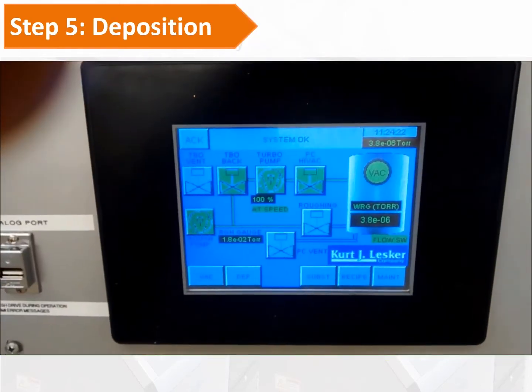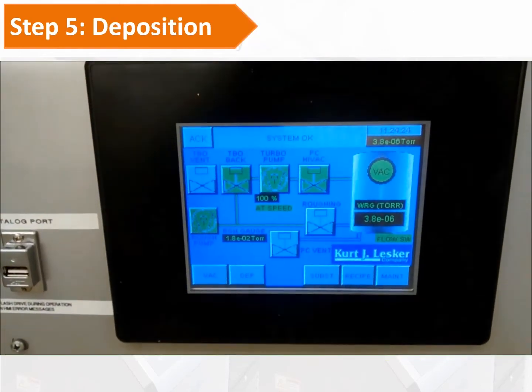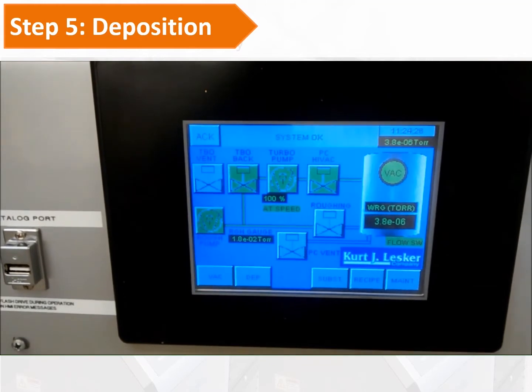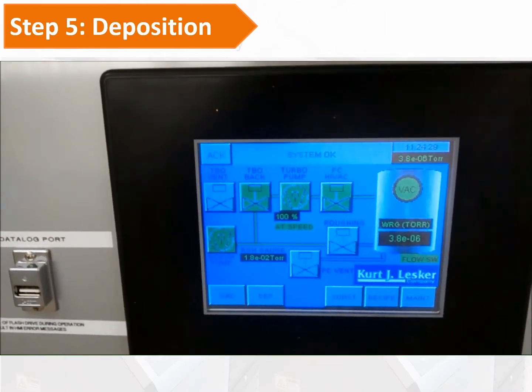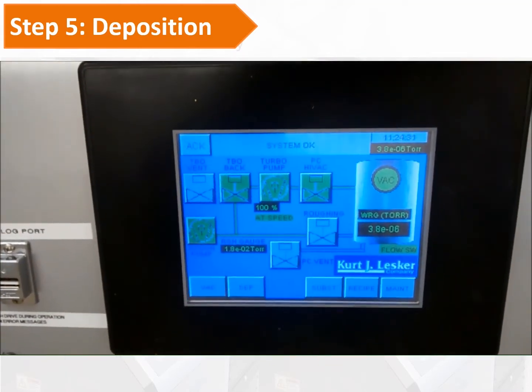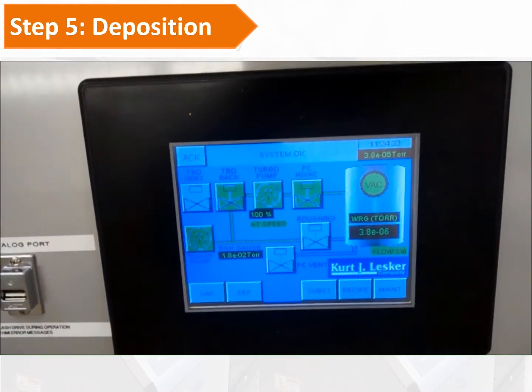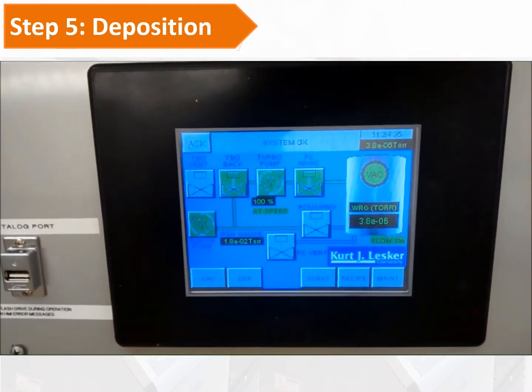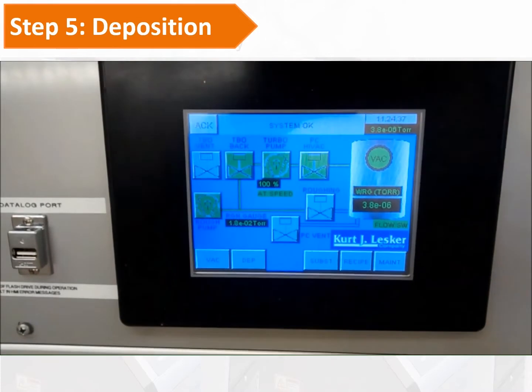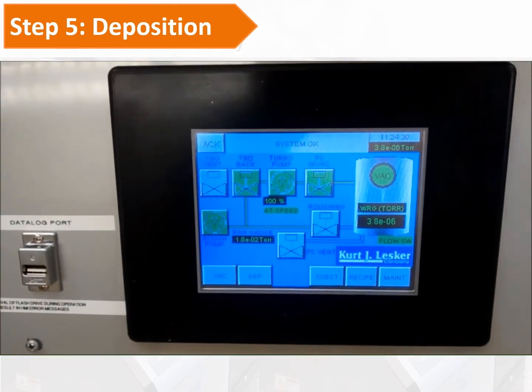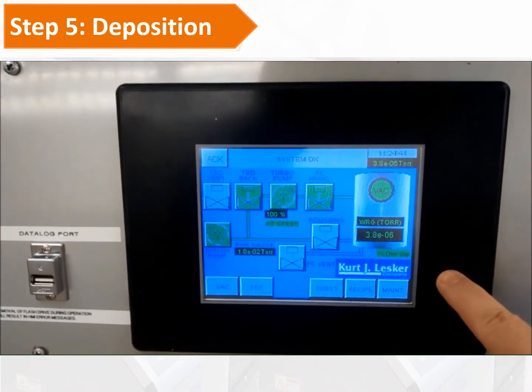Step 5, deposition. When the pressure reaches below 5 times 10 to the minus 6 torr, which usually takes around 5 to 8 minutes after the pumping down is finished, we can go back to the Nano36 touch screen controller.